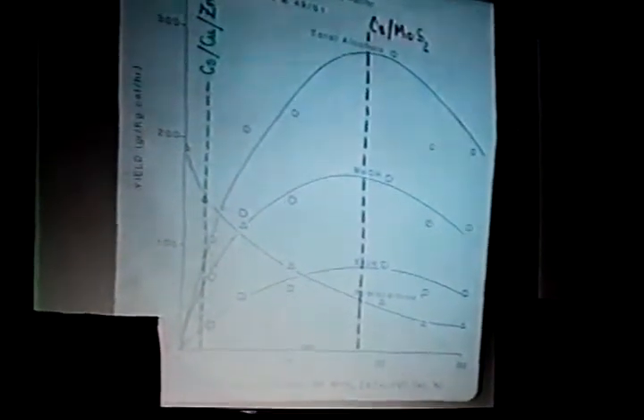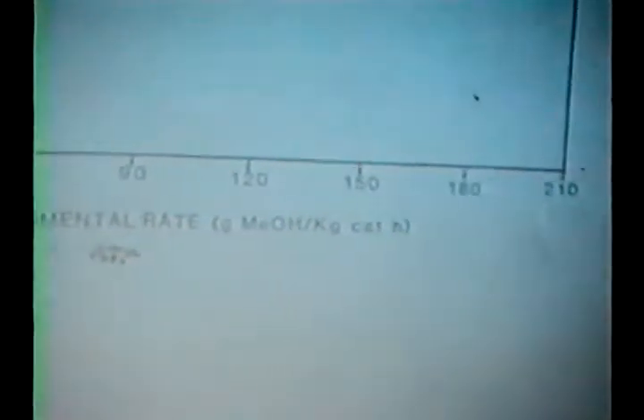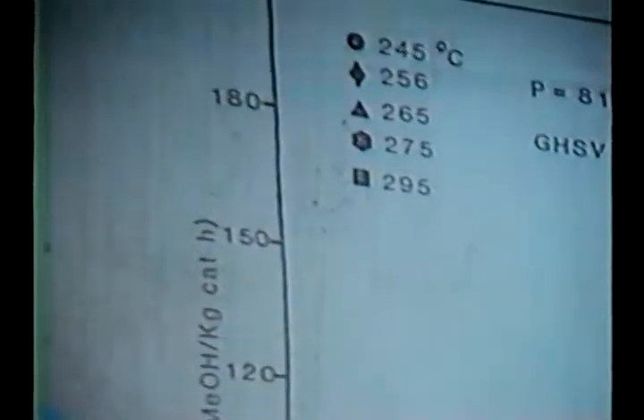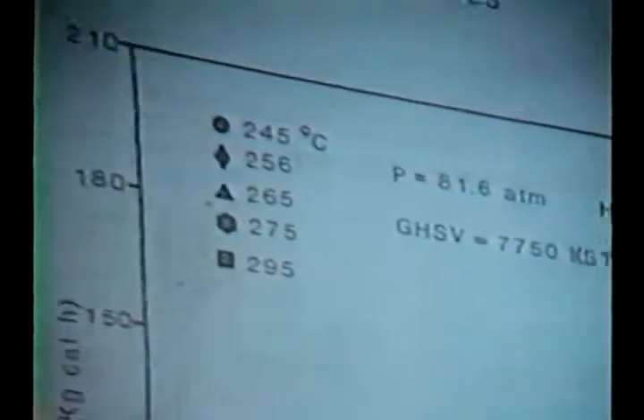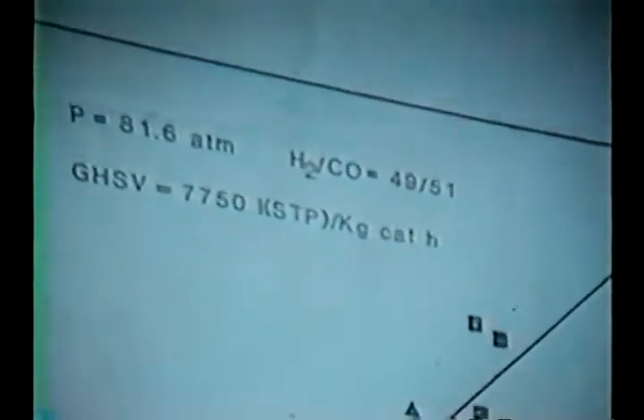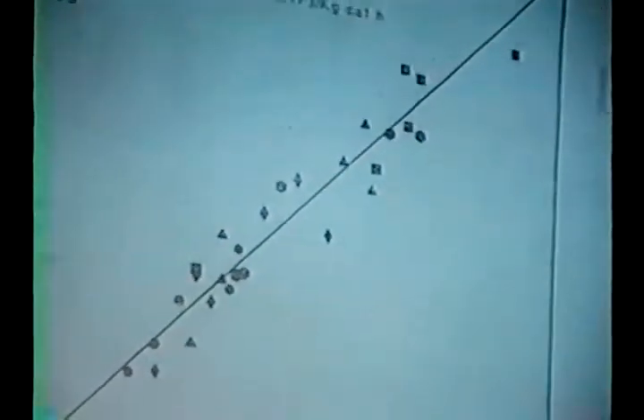We looked at the kinetics of these reactions under a variety of conditions, variety of cesium loading, and we established a correlation which at this time I like to call an empirical correlation, which is fit by an equation where the total weight cesium loading appears in two ways. One is a constructive way and one is a non-constructive way, indicating that the catalysts are bifunctional. In other words, as we add cesium, we promote some reaction, but as we add more cesium, we are retarding some other reactions. And this is a correlation between that equation of the variety of conditions and the experimentally observed rate. All that this equation indicates is that the catalyst is bifunctional.